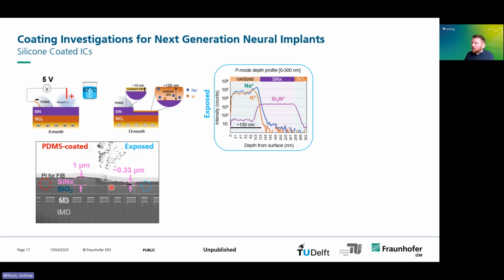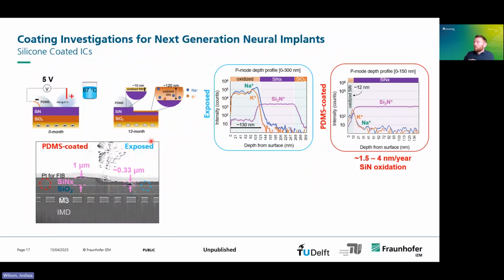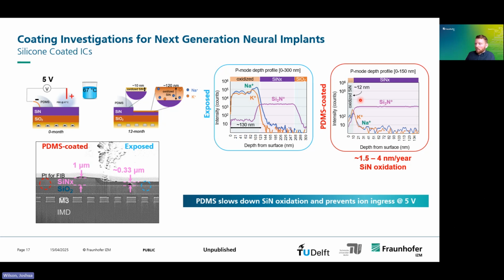Now, how much degradation exactly? If we do a depth profile of these different areas, what we see in the area that was fully exposed is 120, 130 nanometers of oxidation of the silicon nitride, and in the area that was coated with the silicone, we only see 12 nanometers. So what does this tell us? This tells us that by coating with silicone, we can increase the lifetime by up to 10 times. So silicone can really slow down this oxidation or damage of the chip passivation.